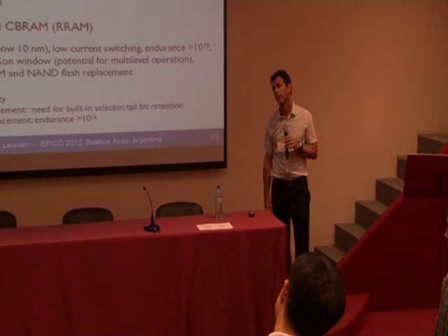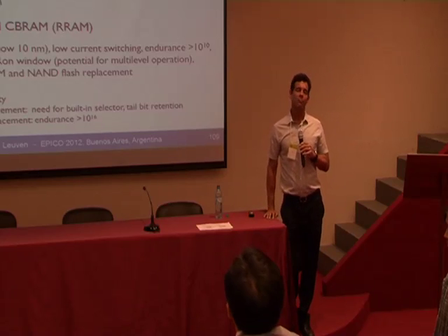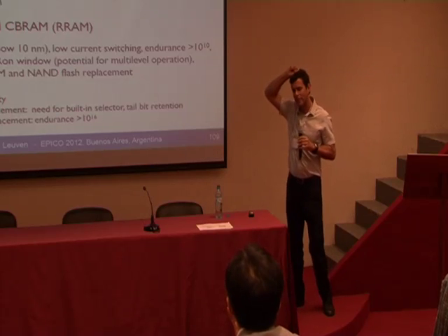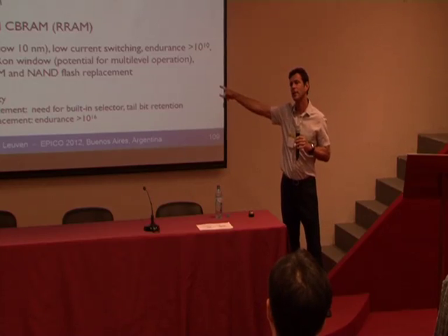I see. But how would that depend on, you put two electrodes and then the distance between them, that's where you're switching something. If you change that distance, and for example, if something is propagating, like this nucleation is propagating, then the time of switching will depend on that in some way. Maybe that would be able to tell you some information. Yeah, no, but unfortunately, as I said, the propagation maybe is misleading. I took what we always show, but it's misleading. It shows that it can be very fast. But what controls the switching in our devices is Joule heating, propagation of heat, not the intrinsic limit of how fast the phase transition can go.